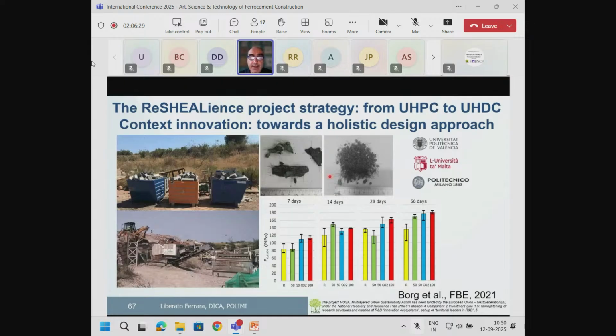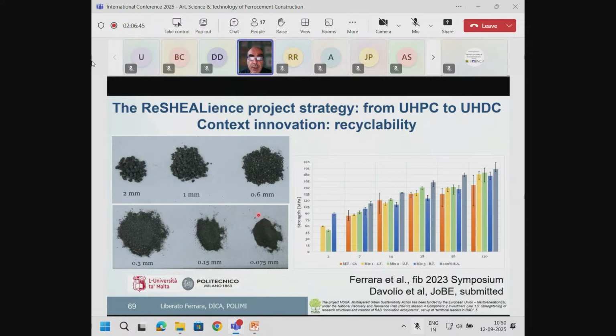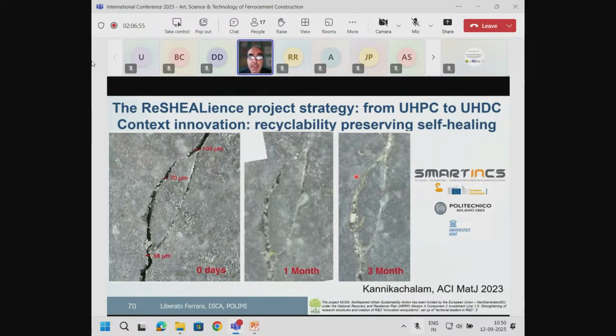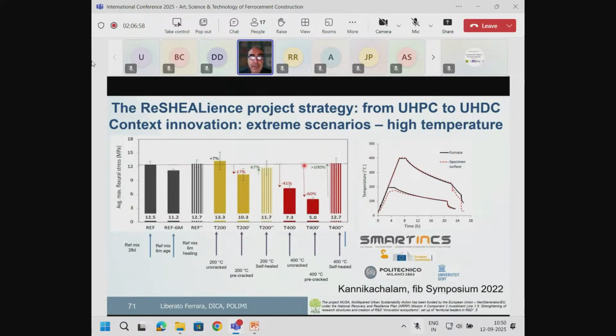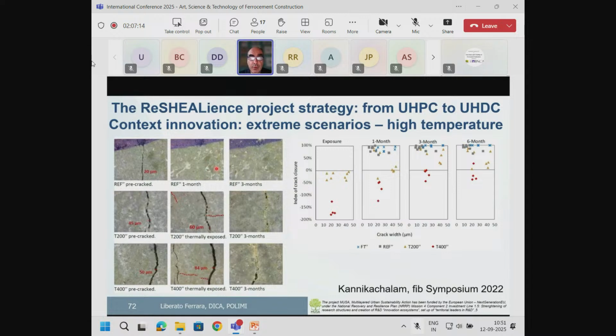We also proved that this material can be recycled with no detriment to the performance. You see, compare the yellow, which is the reference, the other solutions, which are with different recycling percentages. We proved that we can reduce the content of cement, because when you crush this material, there is quite some fine that you can reuse as a replacement of cement. You keep the self-healing capacity, and also we validated use of this material in, for example, post-fire curing. It was exposed to 200 degrees, and then it was recured, and you can see here that it recovered the flexural stress capacity and also the capacity to close the cracks.